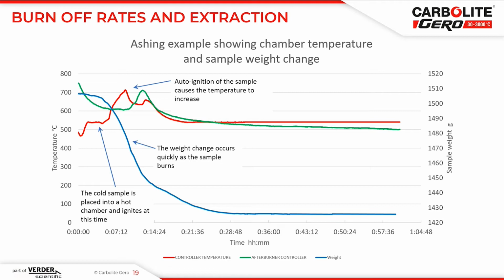540 degrees C. So the rapid increase in temperature caused by the sample igniting will rapidly increase the fumes coming out of the furnace chimney as well, which could overload any fume cleaning method, such as a catalytic oxidizer or an afterburner. Placing the sample in at a much lower temperature and heating slowly by controlling the heating ramp will cause the fumes from the furnace to be spread out over a longer period and will reduce the intensity of the fumes at any one time. That may be an important safety factor for some users.